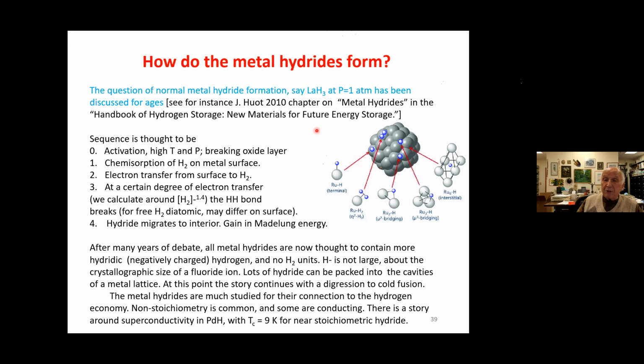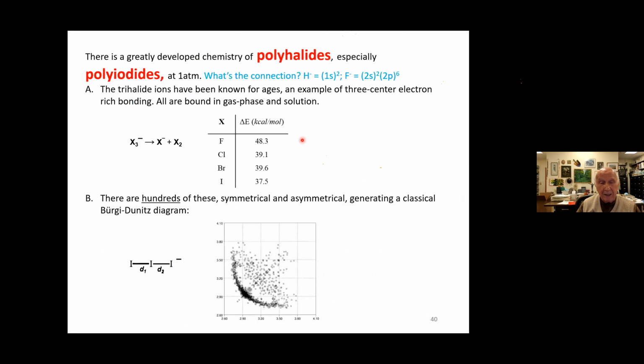The next thing that happens is chemisorption of H2 on the surface. The next thing that's likely to happen is electron transfer from the surface to H2 to make H2 with a partial negative charge. We've calculated around 1.4, the HH bond breaks. At that point, you have H minus on the surface. You see different geometries drawn, and these are not my drawings. These are one of thousands of such drawings in the metal hydride literature. And then the hydride migrates inside the surface to give the metal hydride. There's a lot of room between the metal atoms. Anyway, this is a literature which is there, just waiting to be connected up to the metal hydride story.